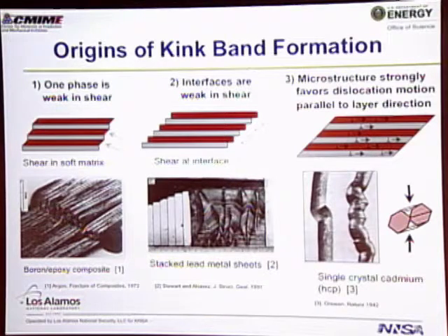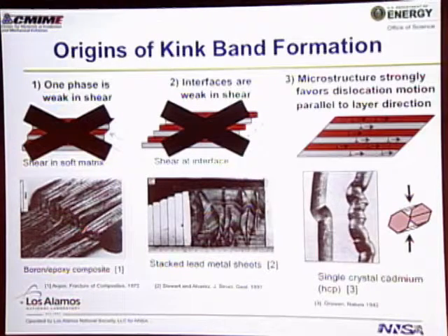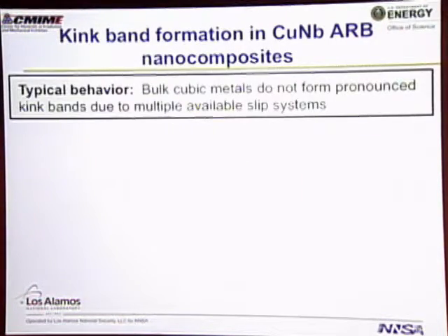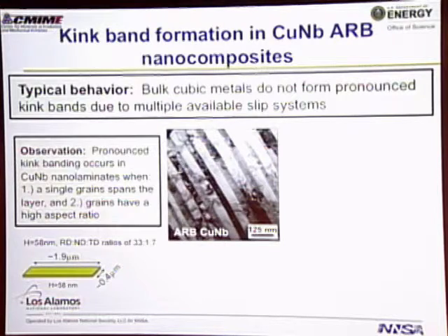And the reason that he saw them was because dislocations in his material were only able to move in just a handful of ways. And so we think that's also what's likely happening in our layered composites, is that our layered structure is making the life of a dislocation so difficult that it only wants to move in one fashion. And so usually we don't see kink bands because the material can slip however it wants.